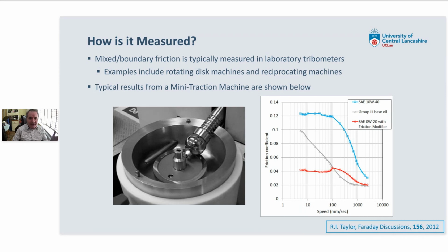lubrication regime. The grey line on this graph is a base oil. So this is a simple fluid with a certain viscosity and no lubricant additives in whatsoever. And then the red line shows a 0W20 formulated engine lubricant, and this time it has both an anti-wear additive in and a friction modifier. This would be a molybdenum based friction modifier. So we can see that in this particular instance, by changing the viscosity grade and putting a friction modifier in, we can go from a friction coefficient of 0.12 down to 0.04 at the lowest speeds. So this simply shows you that changing the lubricant can have a massive effect on the friction that we've got in these lubrication regimes.